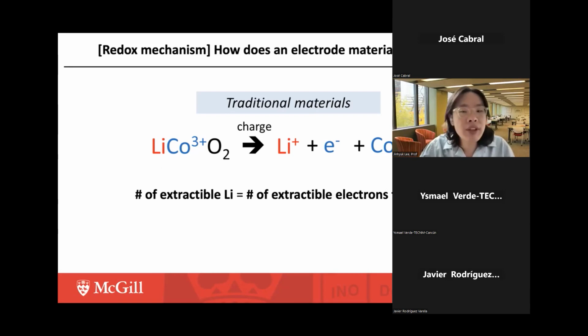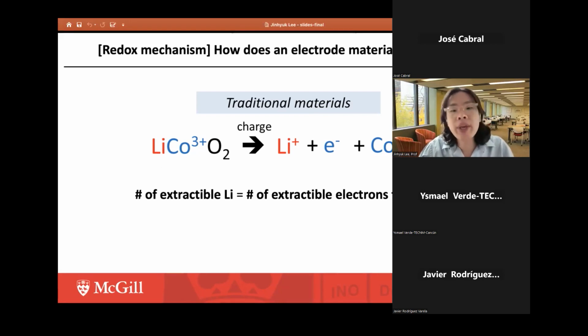Now imagine we extract one lithium from the structure. What happens is that as we extract one lithium ion, we also need to extract an electron from something. And this electron actually comes from the Co3+ in the structure, getting oxidized to Co4+. With this oxidation, there's a release of the electron. So in this traditional material case, we can see that the number of extractable lithium in the structure is the same as the number of extractable electrons from the transition metal oxidation, right? But unfortunately, if you look at this lithium-excess disordered structure composition, we can see that this balance will be broken.